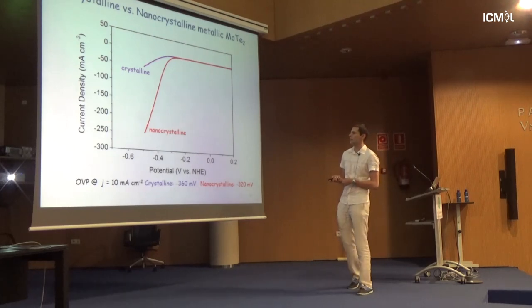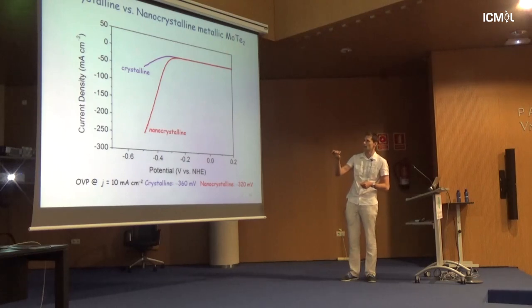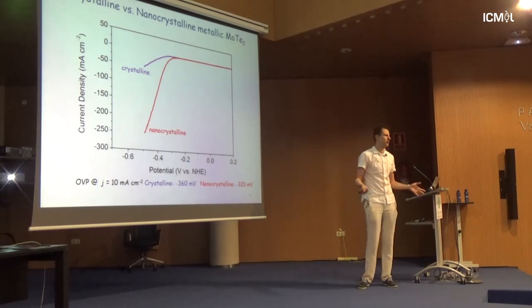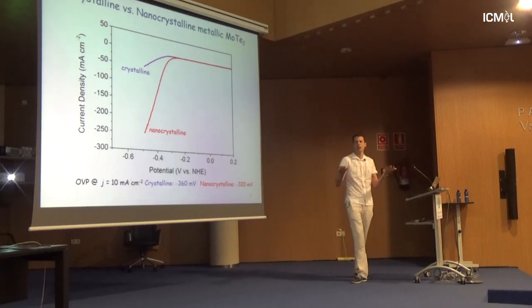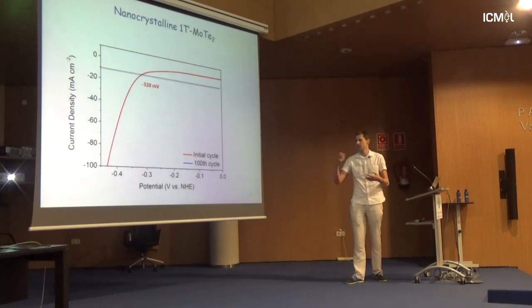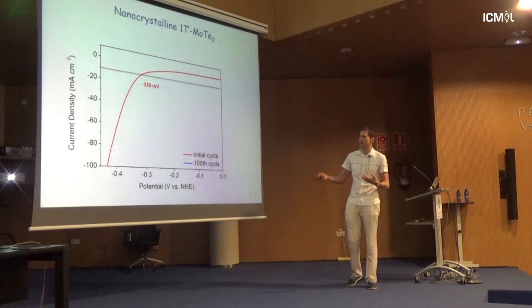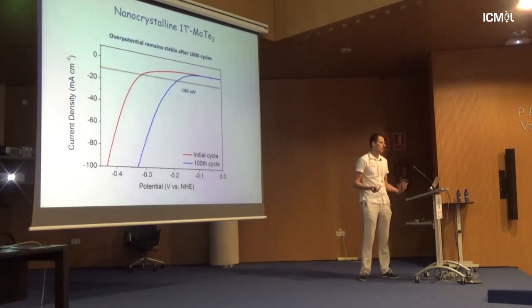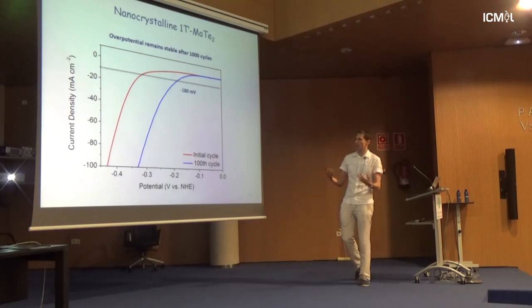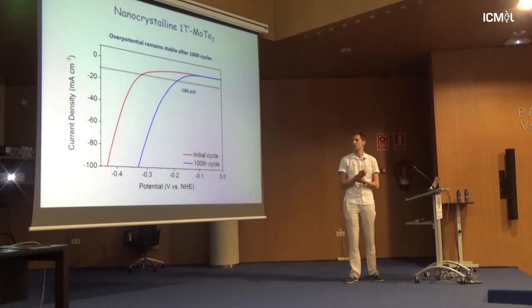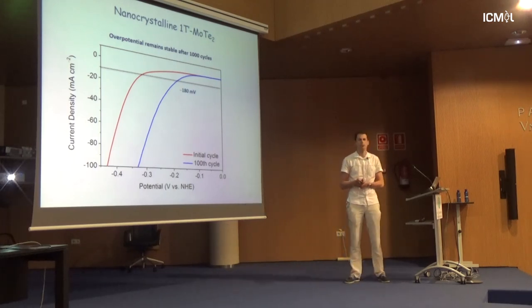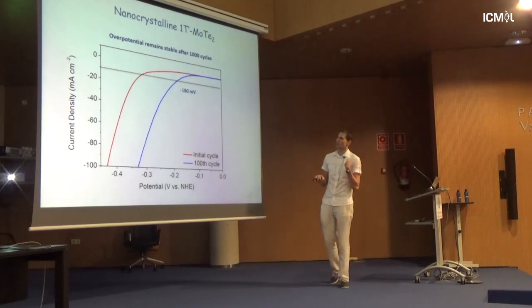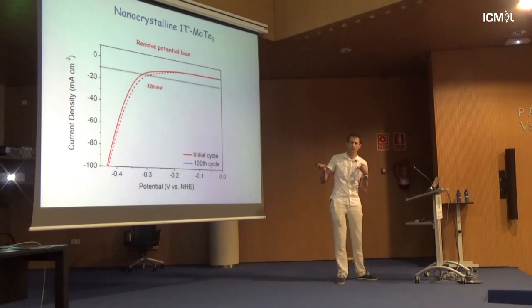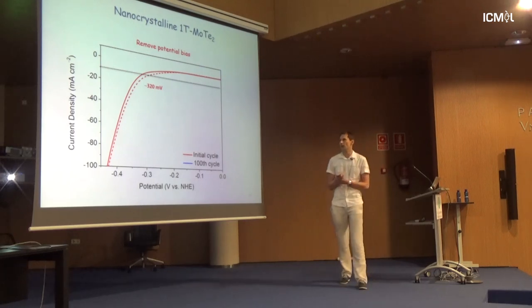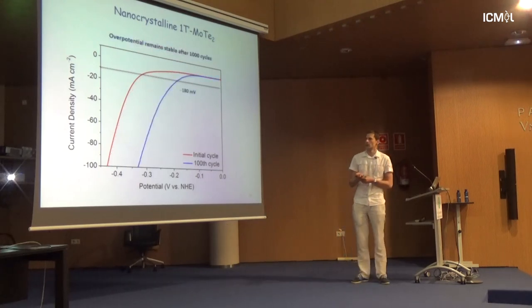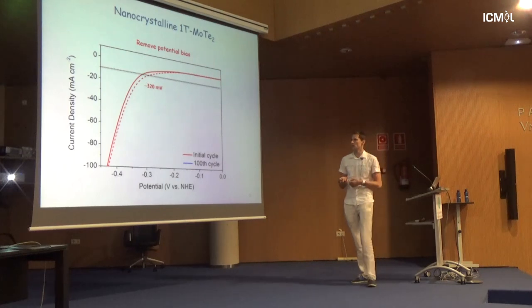And when they nanocrystallize it, it slightly improves the performance, or the current density improves, but this is what you expect. You have high surface area, you have more reactive sites, this is normal. But when they start cycling this material, what we've seen is a massive, dramatic improvement in capability to produce hydrogen, and all the potential dropped absolutely dramatically. But for me, what was really cool is that when you turn it off, it reverts back to your 320 millivolts of potential. So you turn it on, turn it off, and it just continues working.